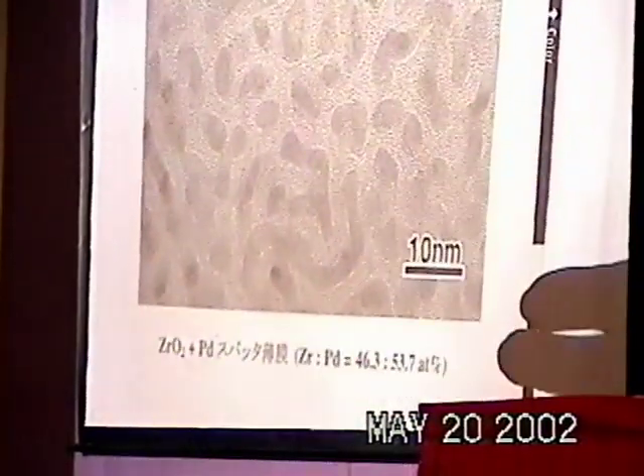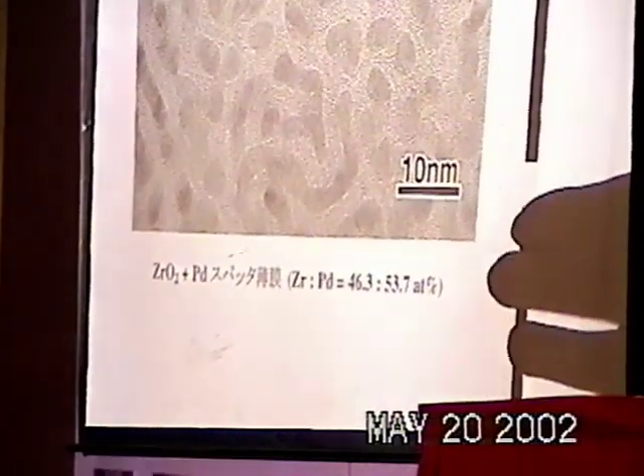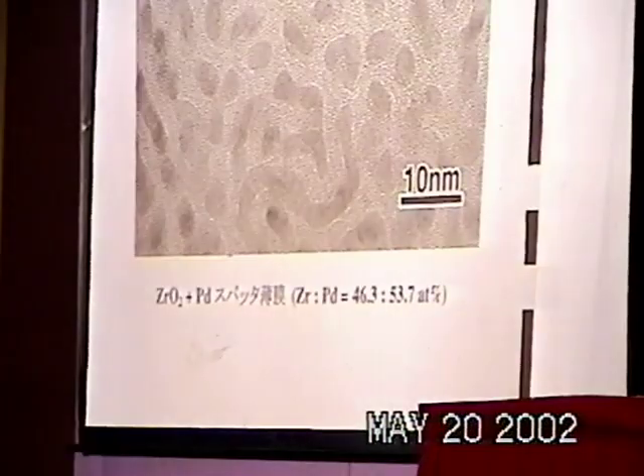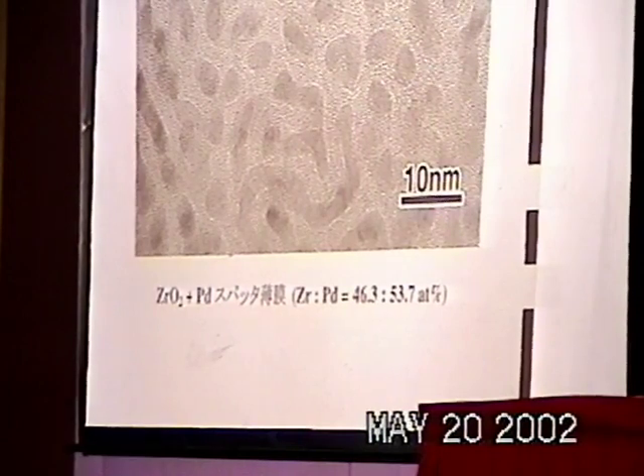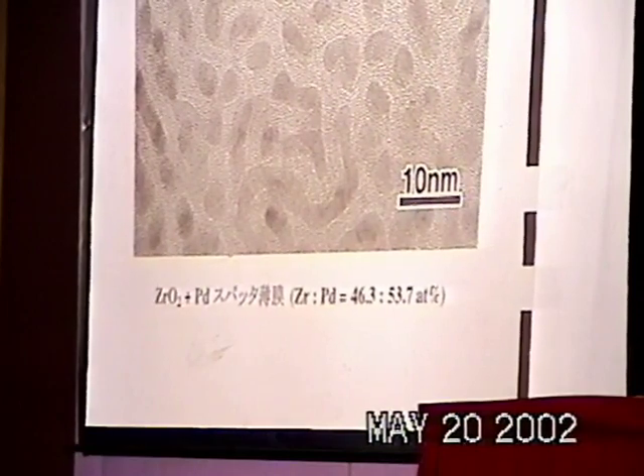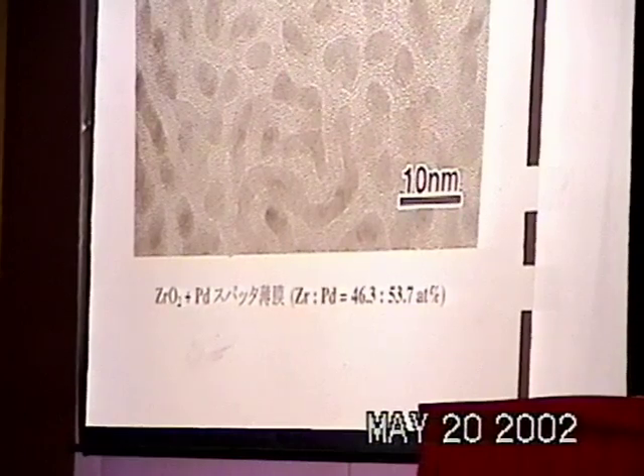This is more detailed microphotographs of 50 angstrom palladium cluster. We were surprised at such beautifully distributed clusters. As you see, palladium clusters are exactly isolated. Just this is a very important event.